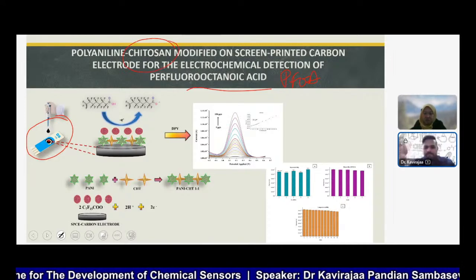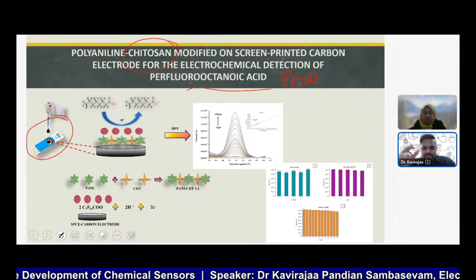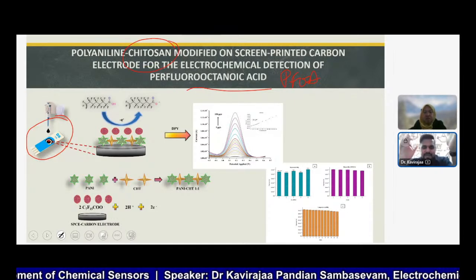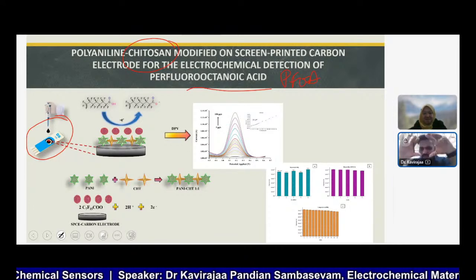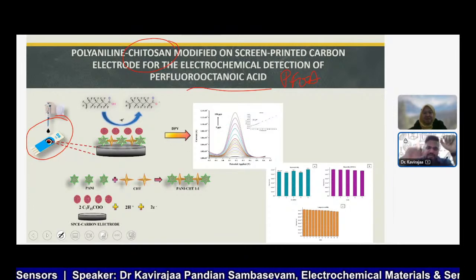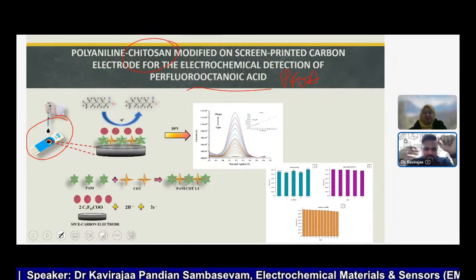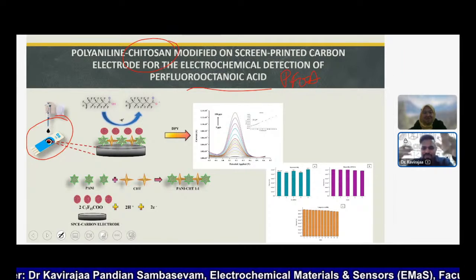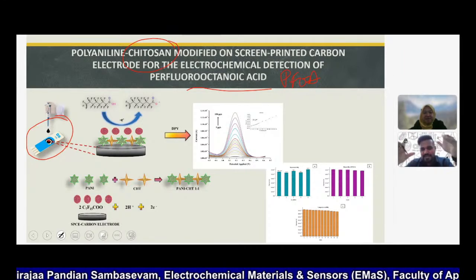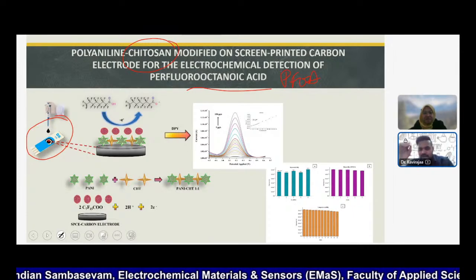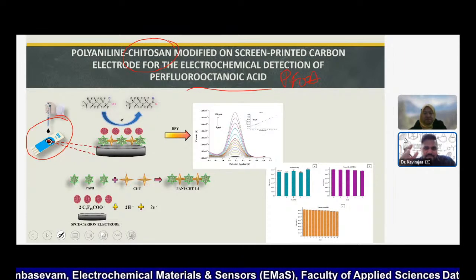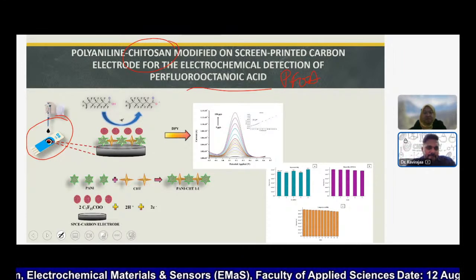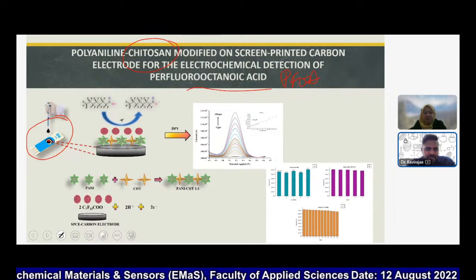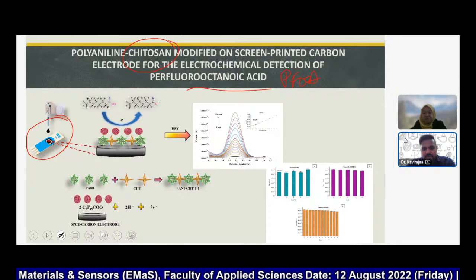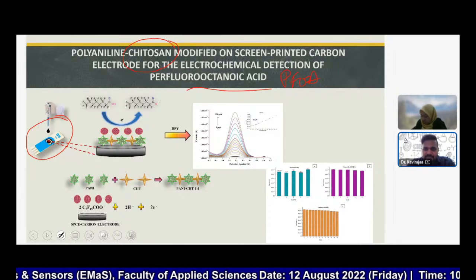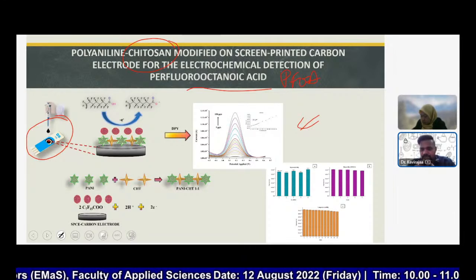But this chitosan, since my topic today is about waste fillers, right? Initially we used crab shells. If you can recall, I did mention that in one of the scanning electron microscope images, it showed some elongated structure, which motivated me to go and study further. Only at that point I realized, okay, this could be due to chitosan as well, because crab shells contain chitosan material, but it's a totally different type of isolation. So we isolated the chitosan from the crab shell, we didn't buy it, we integrated it with the polyaniline, and then finally we used the DPV technique because of sensitivity and also the high resolution.